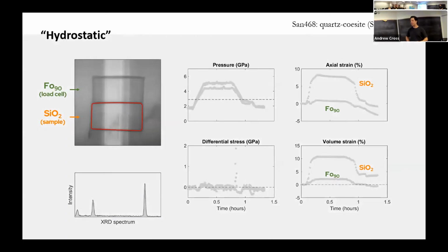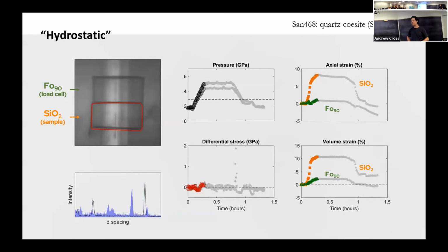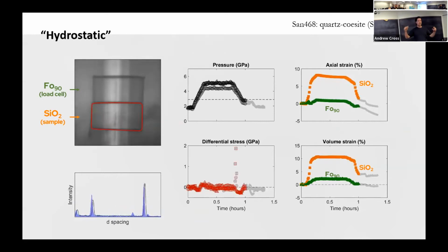All right, let's take a look at this. So we're ramping up through now. You'll see a change in the spectra. Differential stress, there's a little wiggle. The stress drops as we go through the phase transition. We got a big tick up in volume strain of about 10%. Some of that is just because we're increasing pressure, so we're pushing those atoms together. But then this big jump right here, that's the actual phase transition. So that gives us about 6 or 7% volume decrease, and we get about 3 or 4% axial strain just from the phase transition.